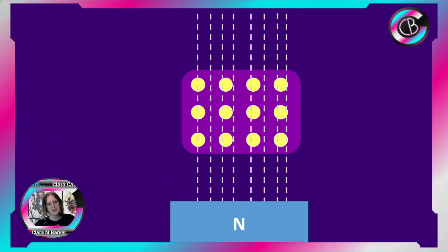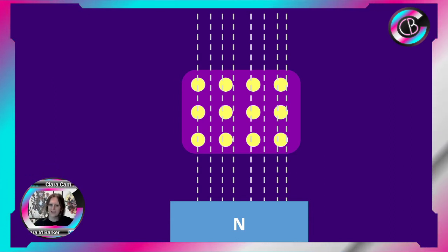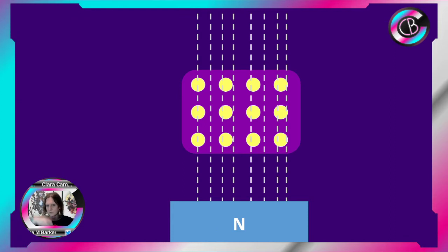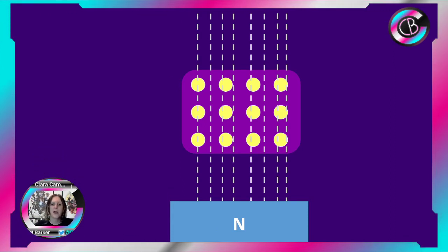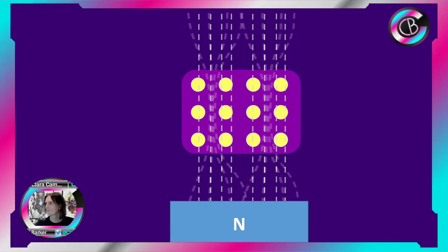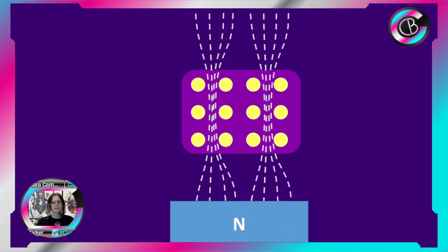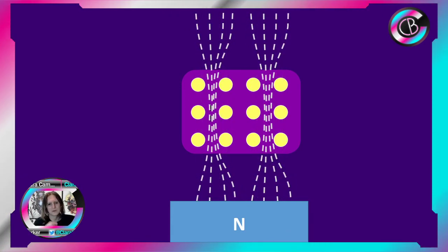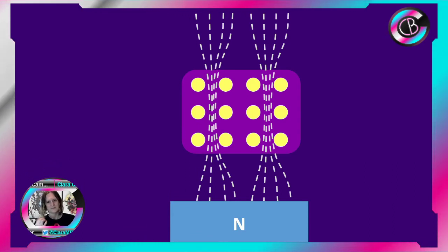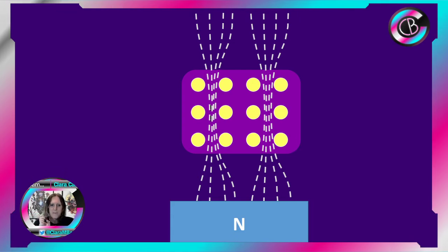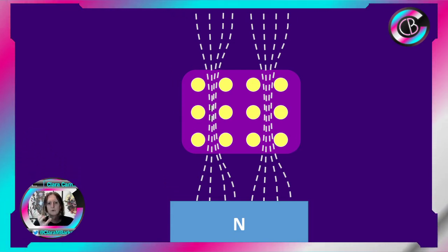whilst they are warm, above their critical temperature, again, the magnetic field just passes through the system like nothing's up. But what happens this time when we cool it down is that the magnetic fields can pass through the superconductor, but they're pinned, they're squeezed. They can only go through the material at certain points.